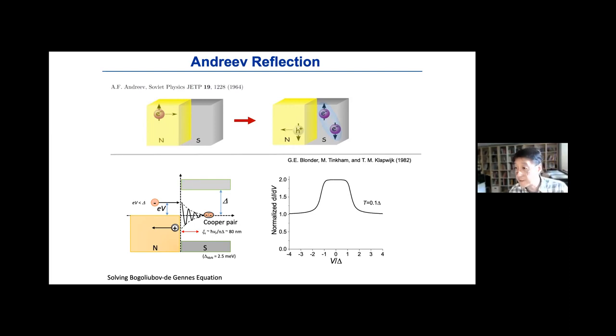Of course, the interface is not perfect, and you start to develop some barriers, and whatever barrier it is, if the Andreev process starts to reduce, then of course this conductance enhancement will reduce. Eventually, if this is complete tunneling of the free carriers, then you expect to see this tunneling conductance type of measurement, or complete suppression of the conductance in between.